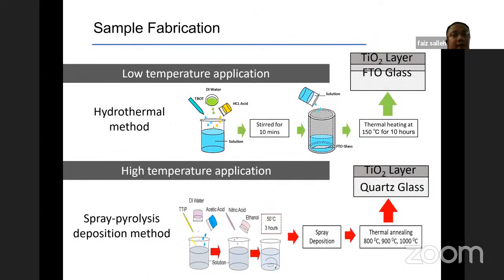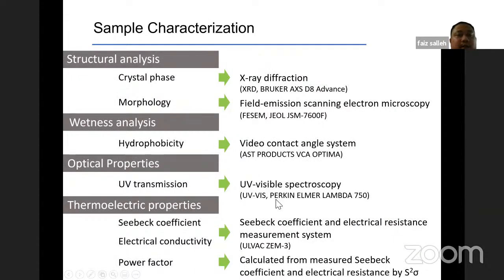So what we do is we propose two kinds of structure. One is for the low temperature application, where we fabricate on the FTO glass substrate by using the hydrothermal method. And the other one is for the high temperature application, where we grow the TiO2 layer on the quartz glass substrate. For this we are using the spray pyrolysis deposition technique in order to grow the TiO2 layer on the quartz glass substrate. Okay, so we have done many characterizations for the structural analysis, wettability analysis, optical properties, thermoelectric properties, and so on.